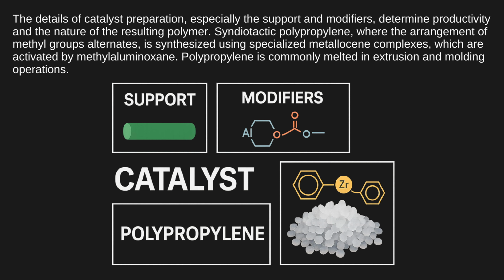Polypropylene's properties depend greatly on tacticity, the spatial arrangement of methyl groups in the polymer chain. Ziegler-Natta catalysts, using TiCl4 supported on MgCl2 and organic modifiers, enable the creation of isotactic polypropylene where methyl groups align on the same side, giving the polymer desirable mechanical characteristics. These catalysts are activated by organoaluminium co-catalysts. The details of catalyst preparation, especially the support and modifiers, determine productivity and the nature of the resulting polymer. Syndiotactic polypropylene, where the arrangement of methyl groups alternates, is synthesized using specialized metallocene complexes which are activated by methylaluminoxane.